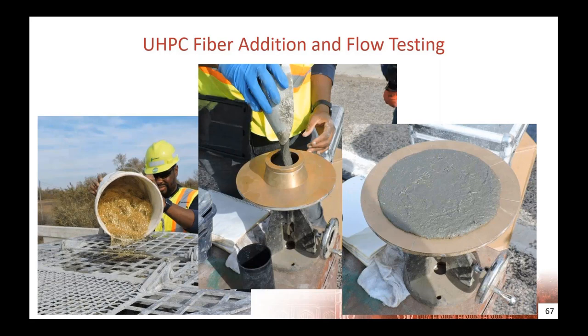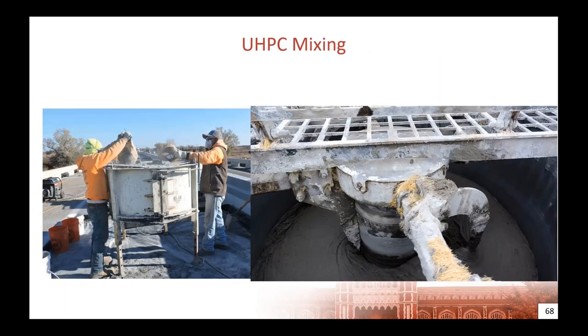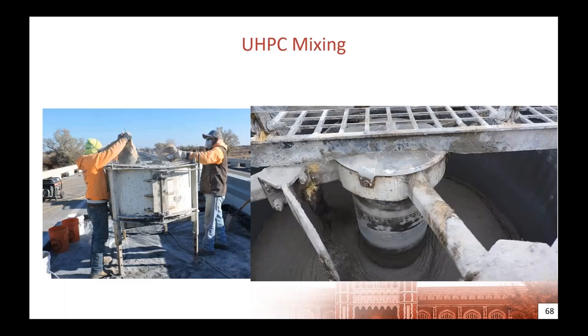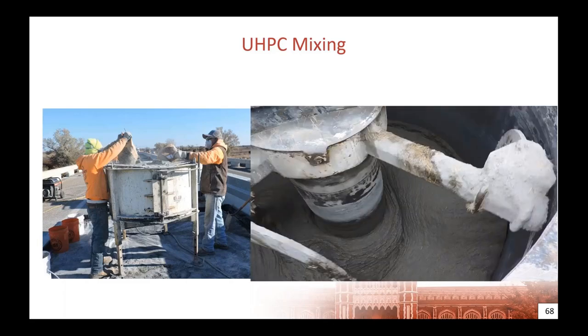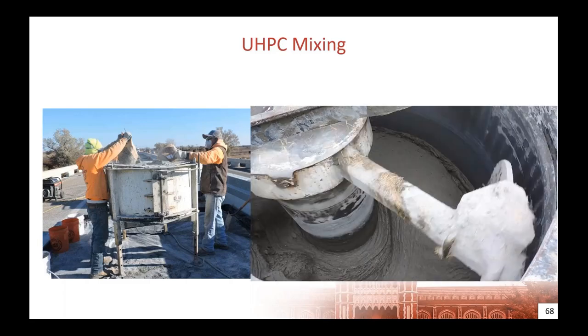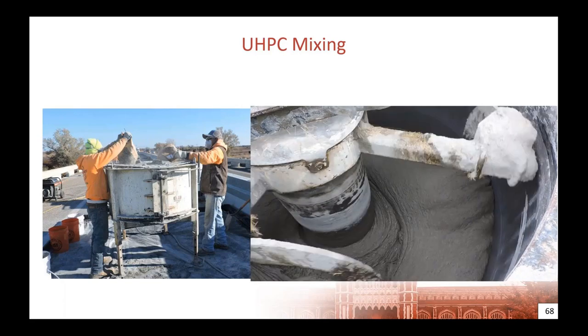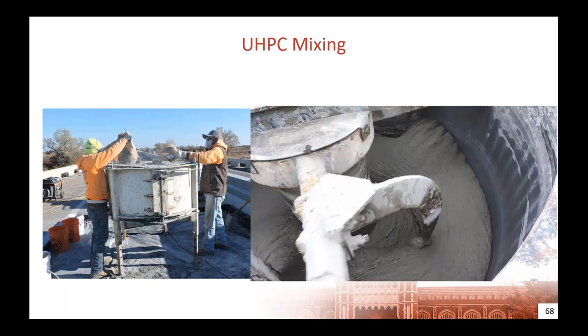And the representative from the company monitored every single batch that was made, because multiple batches were made for each set of pours, and made sure that the flowability was in what they recommended so it could flow. And then if you click next slide again, here's a video of the mixer running with the material in it. And as you can see, it's a very fluid and very thick mixture. It's a highly viscous, very flowable material that moves very slowly, but it'll get to where it's going. It just takes some time.